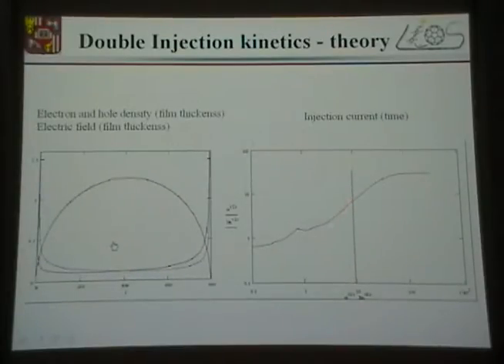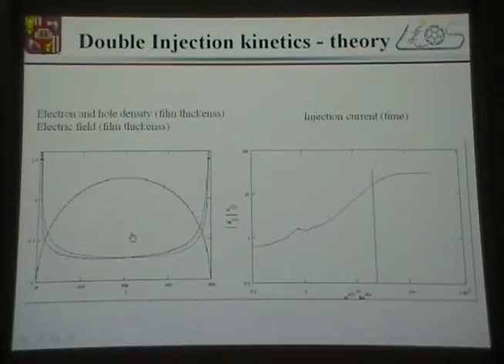We do have experimentally observed a very, very small kink. We observe this kink better if we take the derivative of the curve. And if the recombination would be of Langevin type, which is a typical recombination in low mobility materials, that would be it. So the current would actually saturate here and continue at low level. But what happens in P3HT:PCBM solar cells is that this non-Langevin recombination allows for the charge carrier concentration increase here.